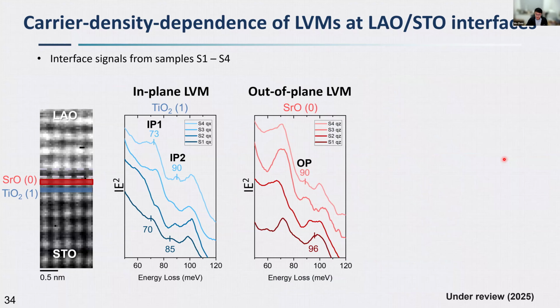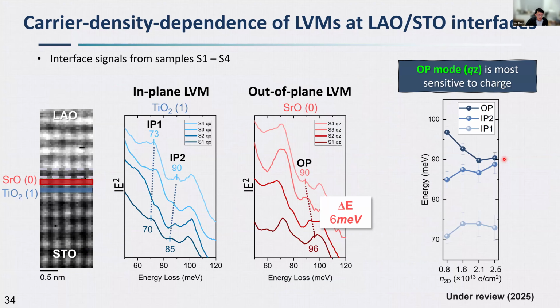Well, I'm not getting into the details here. Basically, what we are seeing here is that we plot the out-of-plane vibrational modes and in-plane vibrational modes as a function of the charge carrier density across these 4 samples, and we're just looking at the end result here. So what we see here is that the out-of-plane vibrational mode is the most sensitive to the charge carrier doping. It changes energy by 6 milli-electron-volt across these 4 samples.